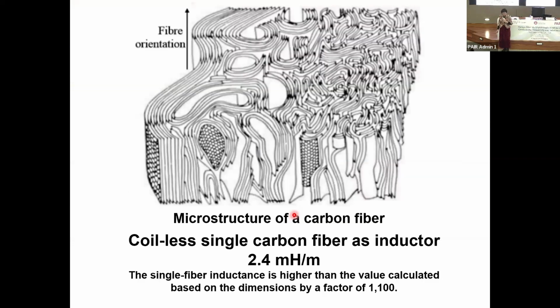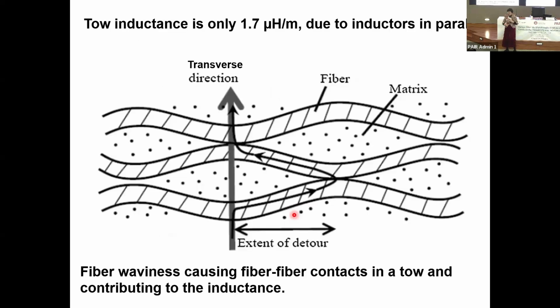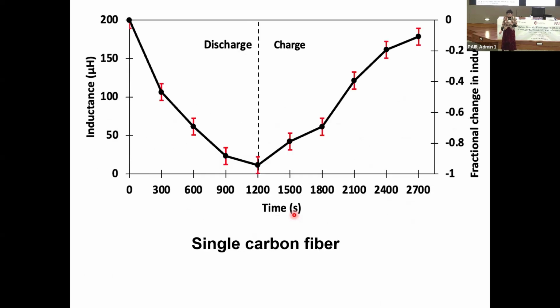And we discovered that the coilless single carbon fiber exhibits very high inductance due to the microstructure. It's 2.4 millihenry per meter. It's higher than the value calculated based on the dimensions of the single fiber by a factor of 1100. The tow, as opposed to the single fiber, is much lower in the inductance, only 1.7 microhenry, not milli, but microhenry per meter. And that's simply due to the inductors in parallel inside the tow.